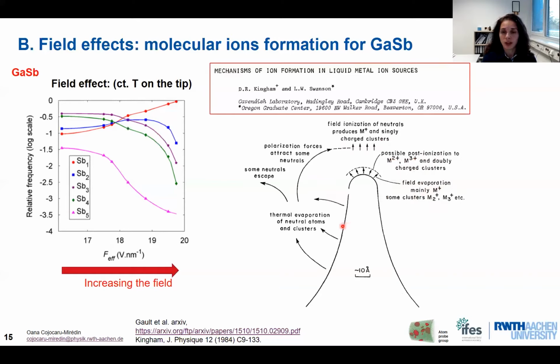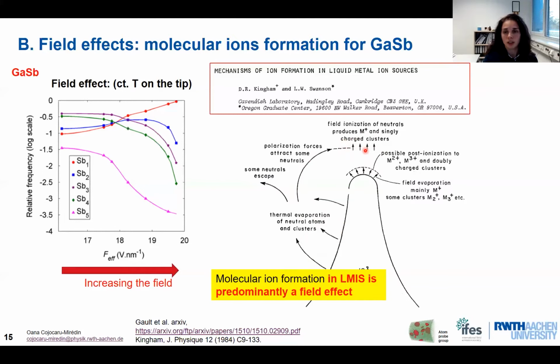What can also happen is that from the side of the tip, we have thermal evaporation of neutral atoms and clusters. Some of them will escape, so will be lost, of course, but some of them will be attracted by polarization forces to the region where we have a high electric field, and these clusters are going to be charged. So this is a possible phenomenon which can be explained for the gallium antimony.